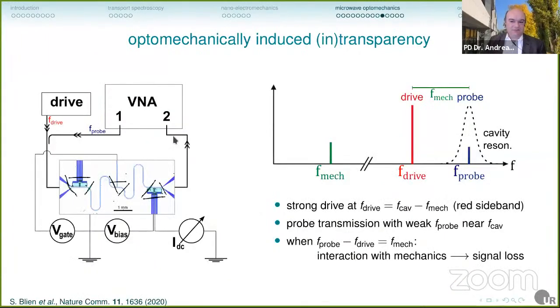Now, we asked what type of experiment should we do to unambiguously prove that there is an optomechanical interaction. And the advice that we got was we should do optomechanically induced transparency. What's that? Well, we apply two microwave tones. We apply a strong drive tone, and that is red-tuned from the cavity frequency by the mechanical frequency. And then we apply a weak probe tone that is swept across the cavity of the microwave resonator.